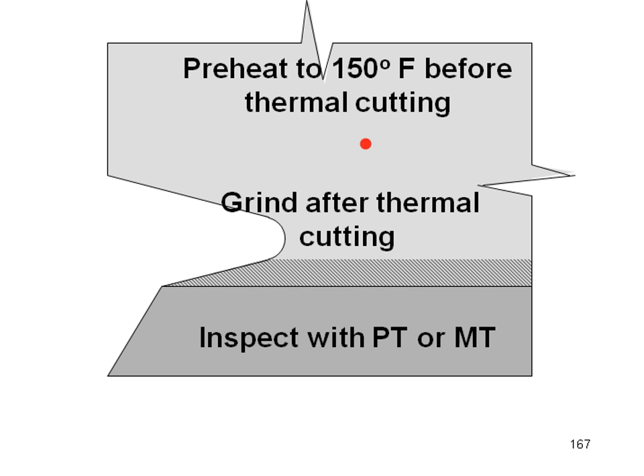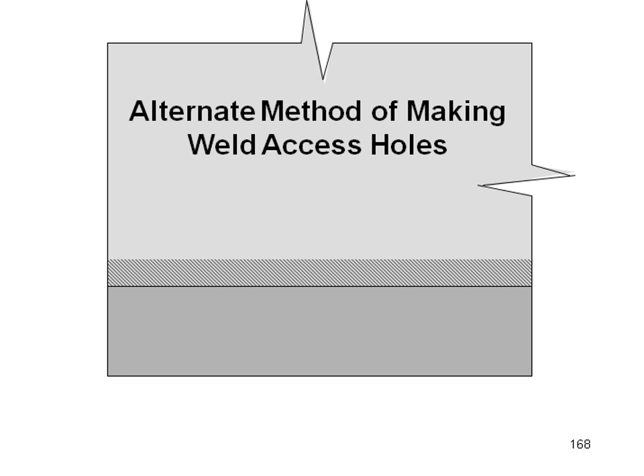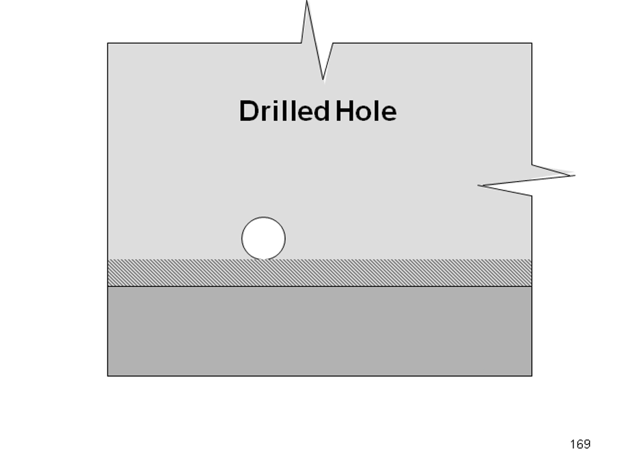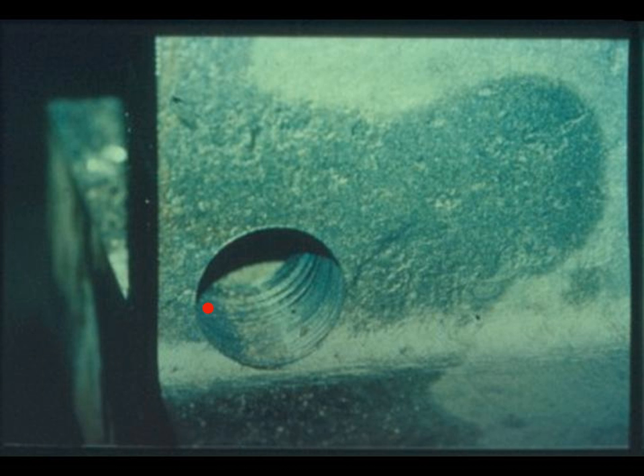After you cut the access hole, it's ground to bright metal. After you grind it to bright metal, you inspect it with dye penetrant inspection or with magnetic particle inspection. The goal is to start with crack-free surfaces. Now that has brought about an alternative practice that I like, and that is you use your drill line to create the hole that will constitute the outside radius of the weld access hole. Now this particular shot was taken before these weld access holes were made bigger. This would not comply, but it is a shot that shows you the drilling of the hole.